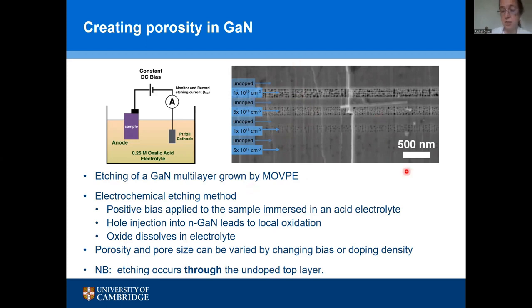When you look at this image, which is a scanning electron microscope image, obviously we can see my porous layers and my non-porous layers. And you might think that we've cleaved a sample with these doped layers in it, and then etched that, and our etchant has penetrated in through this cleaved surface that we're looking at. Now, the thing that's very unusual with our method for creating porosity is, in fact, that this material was etched as a whole wafer, and then we cleaved it to see the porosity later. And the etchant is actually accessing the doped layers through this undoped layer at the top, which appears completely untouched in the SEM image. And as we go through this talk, I'll explain how that can be.